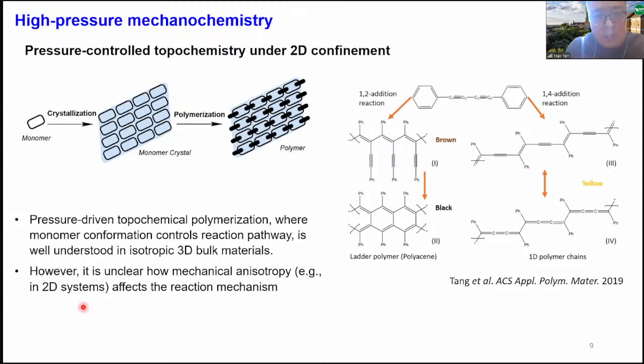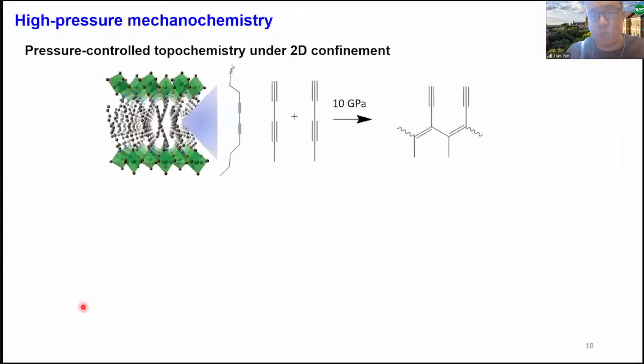Okay, the first one I'll show you is a topochemical polymerization of conjugated diacetylene. This is a reaction not entirely new. People know that if you put conjugated diacetylenes together in a solid crystal, you can drive the reaction by heating, by light, or by pressure. And the guiding principle here is the so-called topochemical selectivity. It means that the active sites that get spatially close to one another tend to react together and form new chemical bonds. In this particular case, we're looking at a so-called 1,2 addition, where carbon 1 in the first diacetylene attacks carbon 2 in the adjacent diacetylene, forming a new bond, and eventually this polymerizes into a polyacetylene kind of structure with a triple bond as the side group.